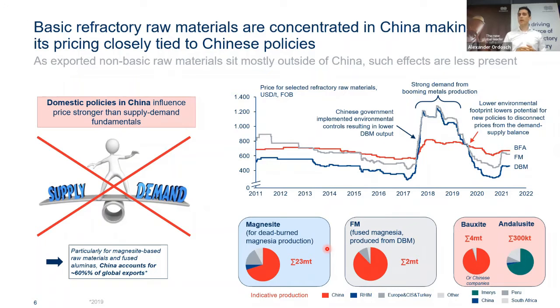In the price chart that you see in the top right of the slide, we can see what happens if the Chinese government cracks down on certain industries. So I lined up here 3 prices of key refractory materials. DBM, dead burned magnesia, so basically magnesite, then fused magnesia, the downstream product, and then BFA, which is brown fused alumina, a downstream product of refractory grade bauxite. And you see that prices went down consistently since 2011 because the global industry is structurally oversupplied, and therefore there is just too much there.